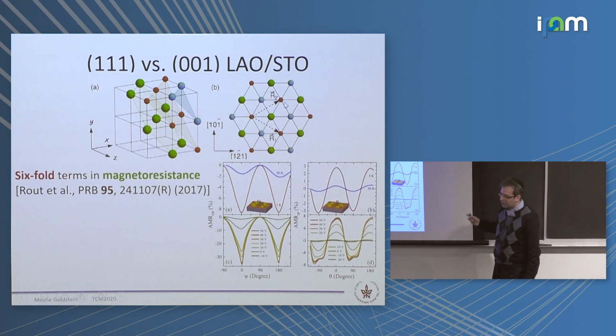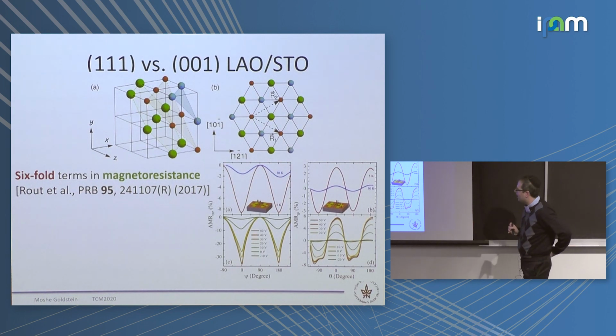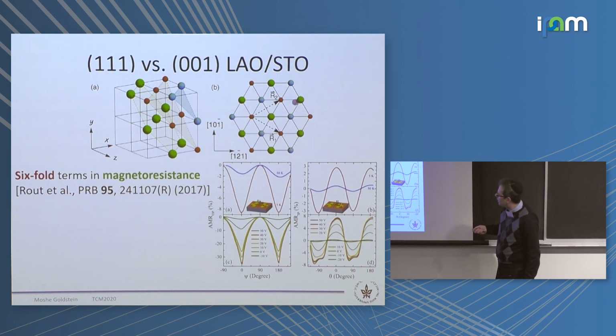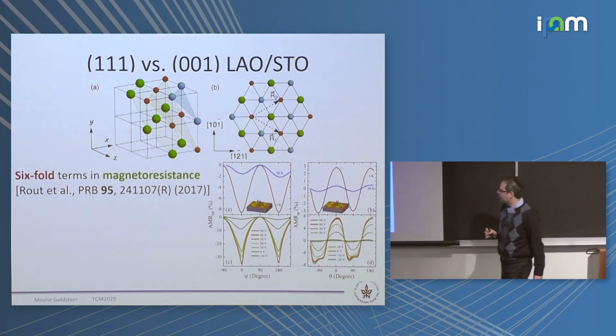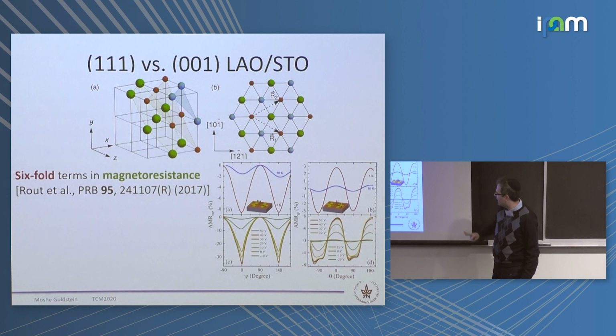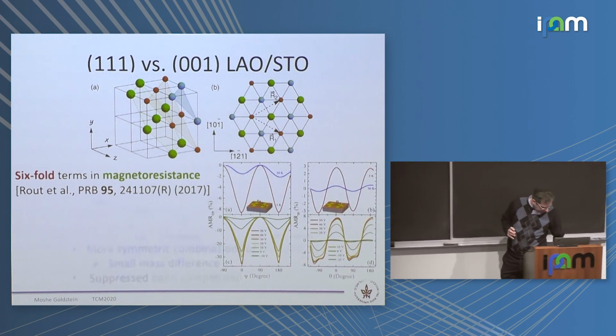So I guess at least here I connected a little bit to the graphene that we have seen throughout the conference. But in any case, you need some more work in your Hartree-Fock, because actually you need to include at least 3 layers before things repeat themselves in this direction. So you have many more orbitals. Basically, you have an 18 by 18 Hamiltonian instead of 6 by 6, but still much easier than twisted bilayer. So in any case, you have this 6-fold structure, and actually you see in magnetotransport a 6-fold symmetry in AMR, but this is not the important thing here.